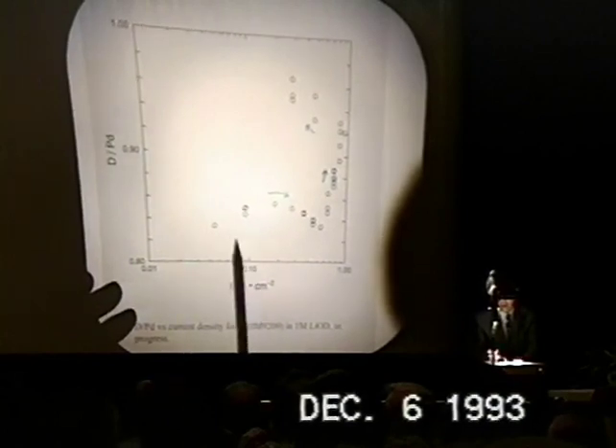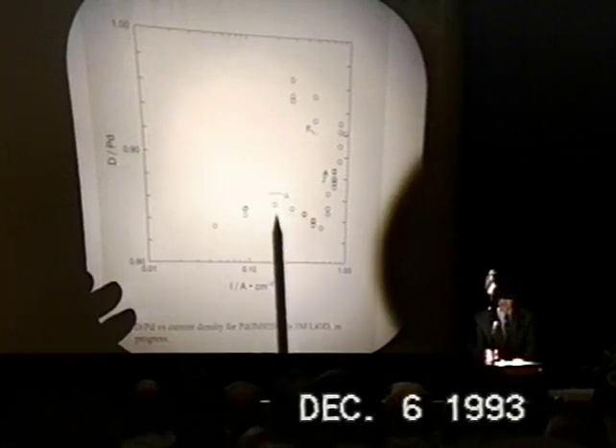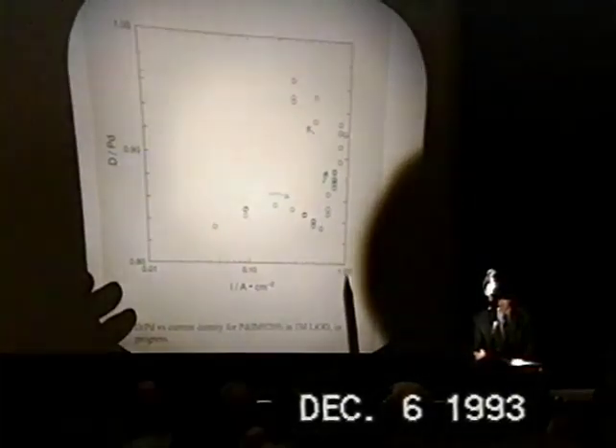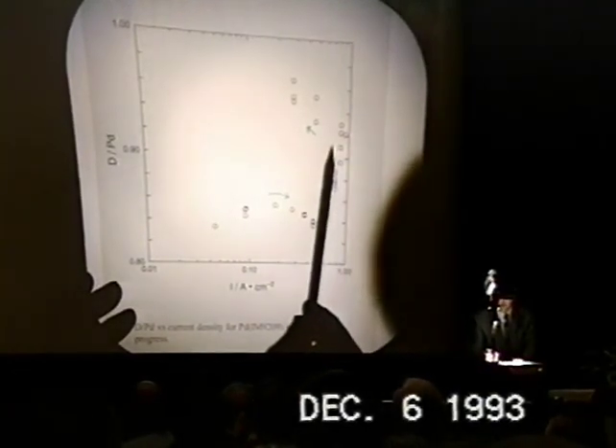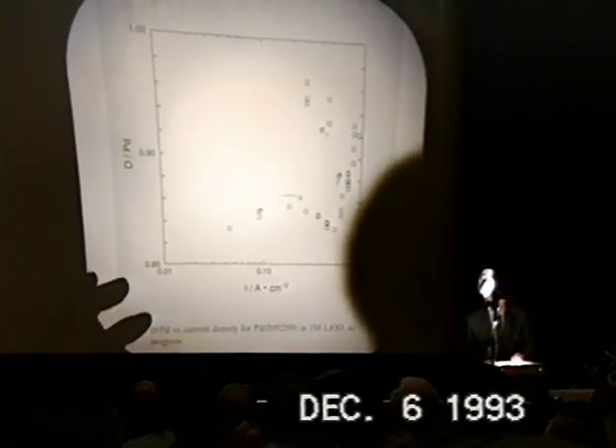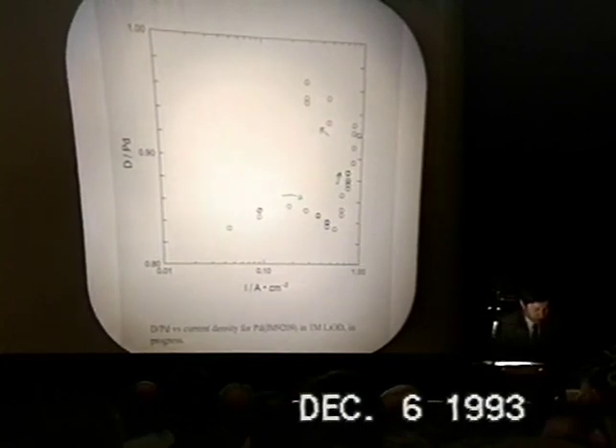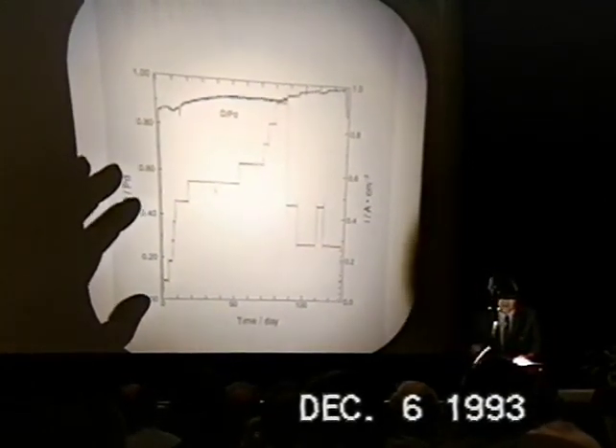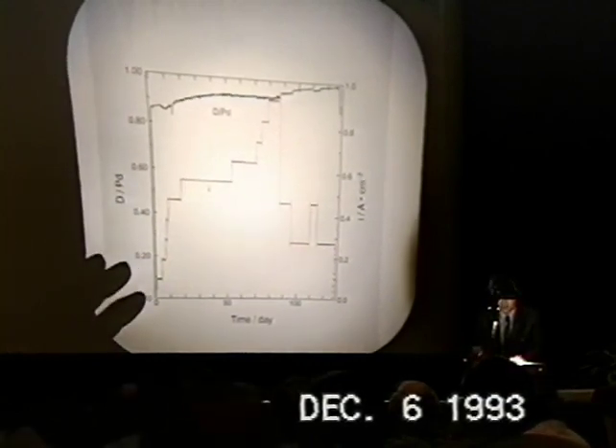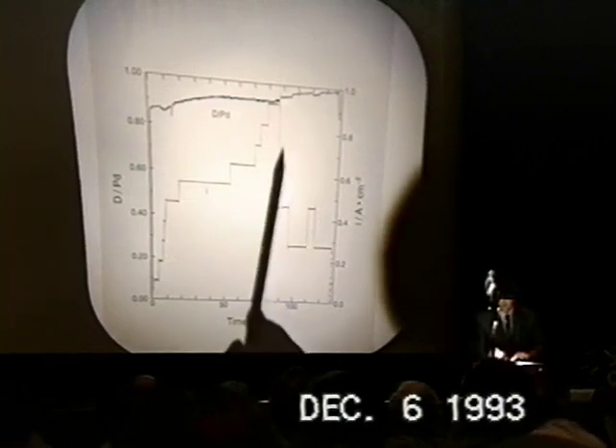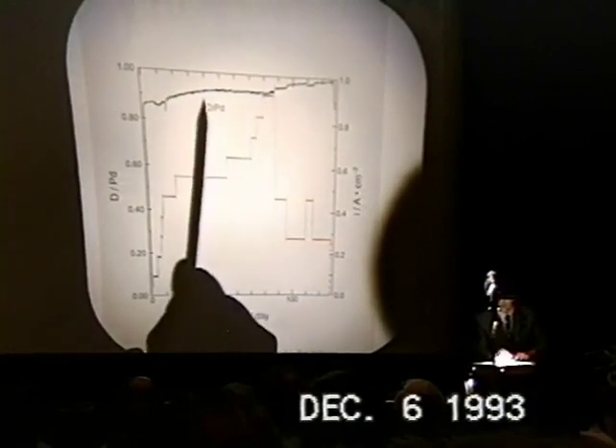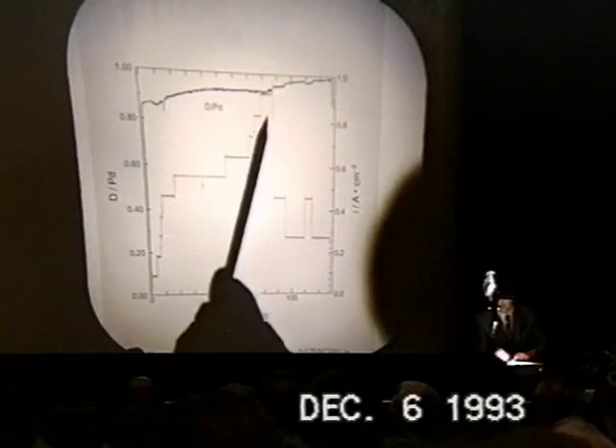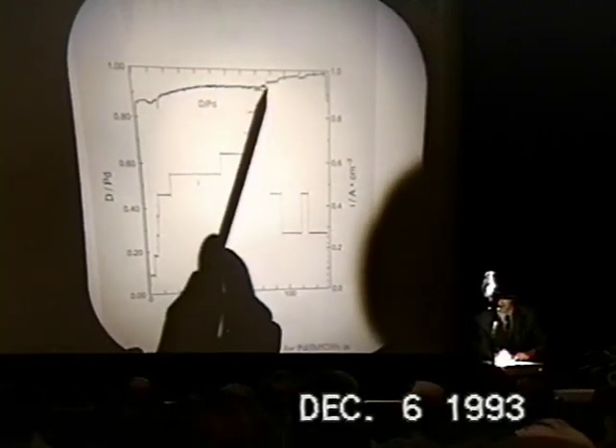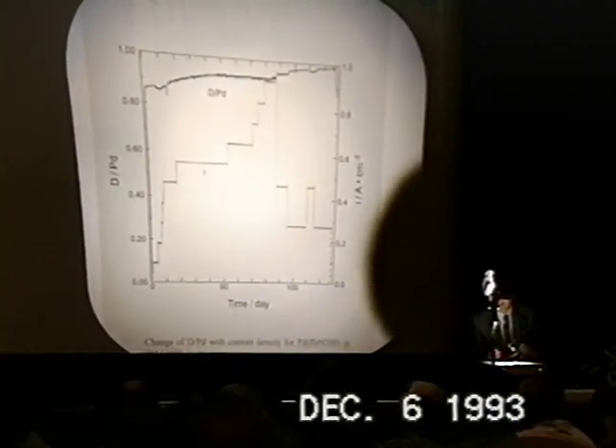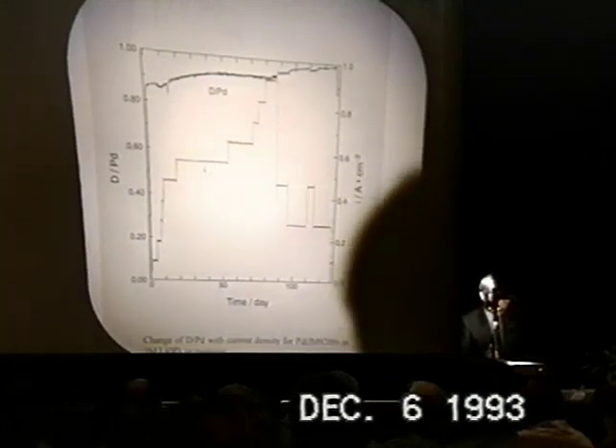As a function of current density, the loading ratio is somewhere around 0.86. Then, close to 1 ampere per square centimeter, it went up. Then, when we went back to lower current density, it went up again. And we did not understand this. This is very clearly seen in this raw data showing all the data during the electrolysis period, which is nearly 4 months. Up to here, we have a very steady increase of loading ratio as a function of current density. But when we decreased the current density at this point, the loading ratio went up without taking much care of the decreasing current density.